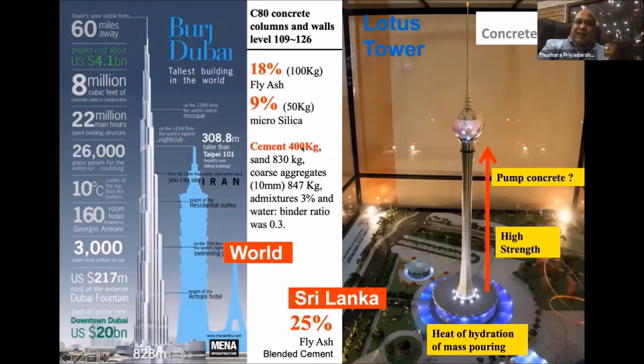So a very interesting thing is, in Sri Lanka, probably you use 400 kg of cement for grade 40, 45 concrete. But here for grade 80 concrete, they have used only 400 of cement and sand, something like this, because these are self-compacting. The amount of sand and the amount of aggregate is almost the same. And as the Professor mentioned, when you go for higher strength, it is better to reduce the size of aggregate, because aggregate weakness becomes very critical in high strength.